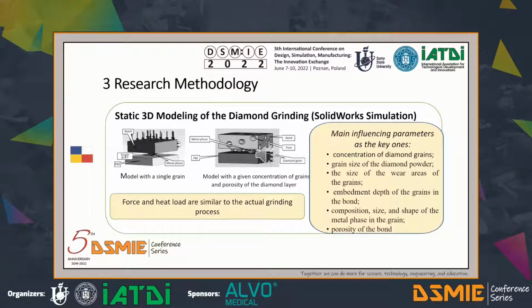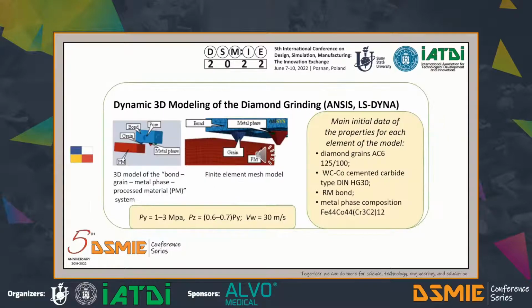The next slides are focused on the research methodology, which consists of two directions: static and dynamic modeling. The static modeling research methodology was based on the use of the SolidWorks simulation. The main influencing parameters were the concentration of diamond wheel grains, the size of the diamond powder, size of grain wear zones, embedment depth of grains in the bond, composition, size, and shape of the metal phase in the grain, and bond porosity.